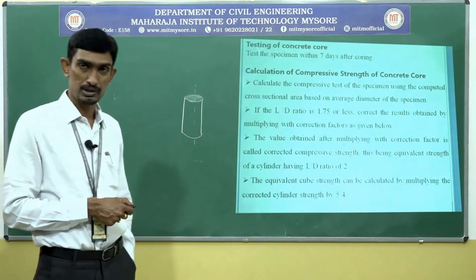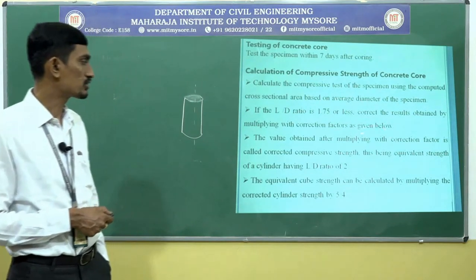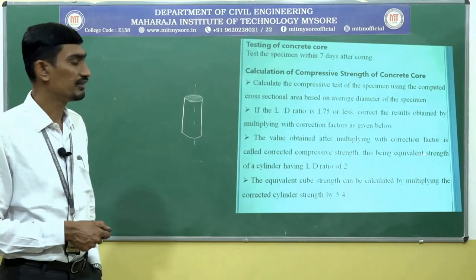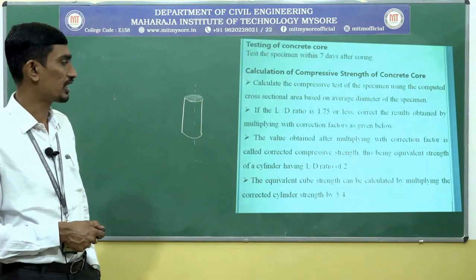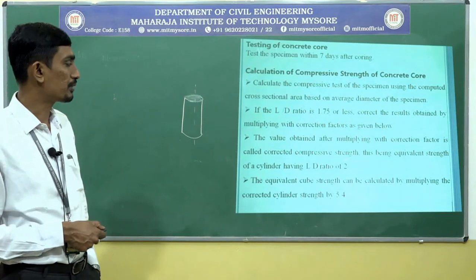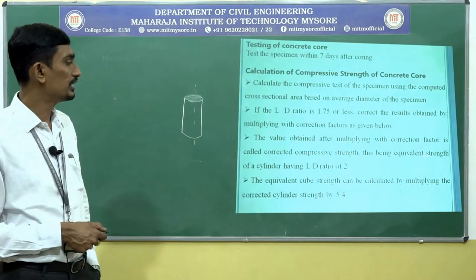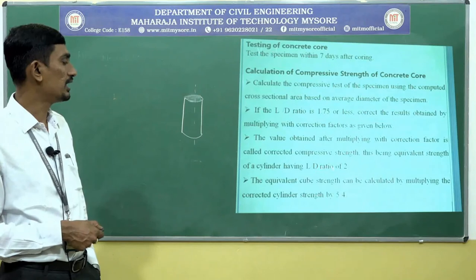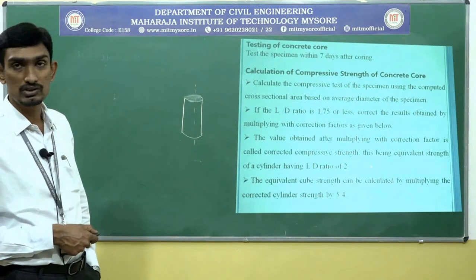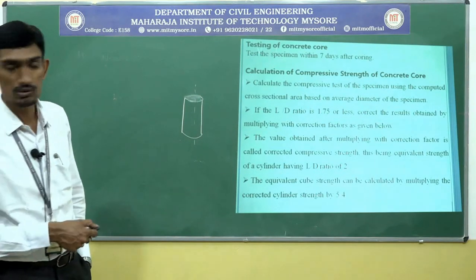So now if you subject this concrete core specimen to a particular load, you are going to get the compressive stress. Whatever compressive stress you get, multiply that with the corresponding correction factor. That will be the corrected compressive strength. This is the equivalent strength of a cylinder having an L by D ratio of 2. So this procedure I am going to teach you now.